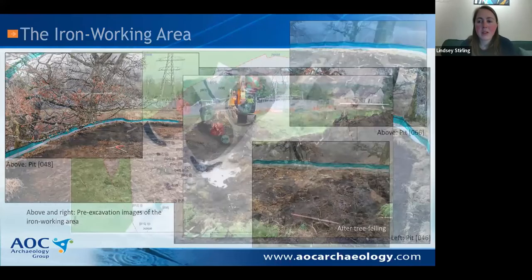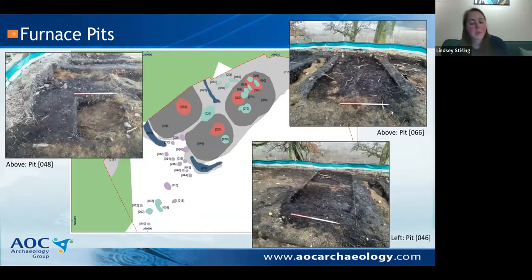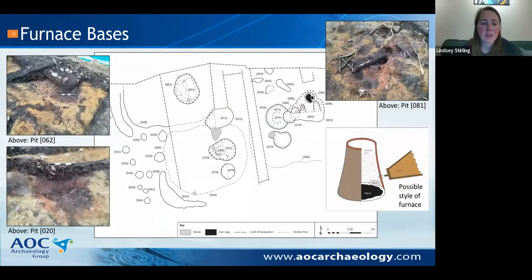So looking more specifically now at the furnace pits themselves, as I say, there were 3 separate pits on the site, and these were the main features of the ironworking area. Each pit was about 2 meters by 4.5 meters across. They had quite steep concave sides, and they were basically just filled with more of this same sort of metalworking debris material, full of charcoal and slag, quite mixed, and just hard to distinguish from the material that had been spread across the surrounding area. But as the team excavated to the base of these features, they were able to start identifying further features at the bottom, which looked like the actual locations of the furnace bases.